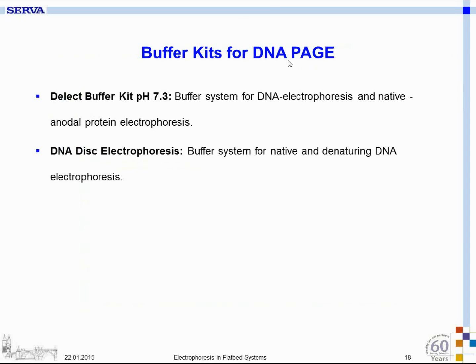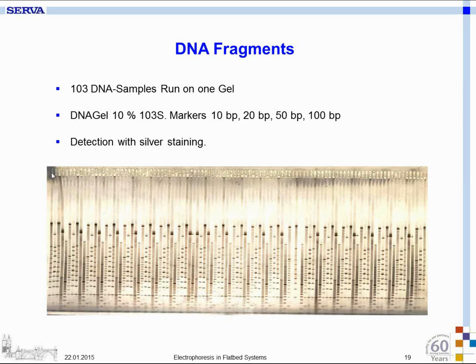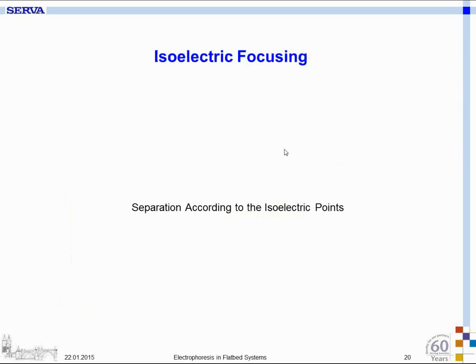And then we also have, for DNA fragment polyacrylamide gel electrophoresis, 2 choices: the Delect Buffer Kit, which is usually directly used in the gel, gives very, very high resolution, very sharp bands, also for small fragments, and then a DNA disc electrophoresis buffer, which can be used as native or denaturing DNA electrophoresis. And here you see the gel that we can supply with the most sample wells, namely 103. This is being used for DNA fragments, quality control of DNA synthesis, but this can of course also be used for proteins. Here detection was performed with silver staining of the DNA fragments.